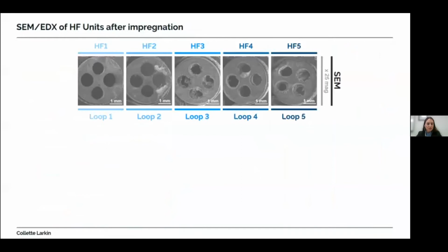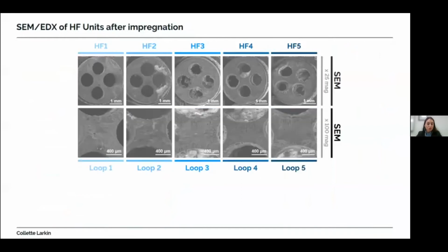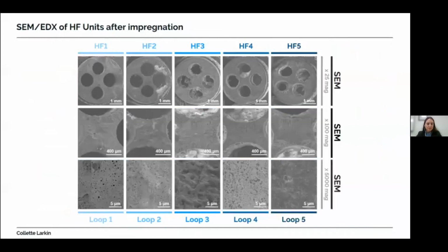And to get a better understanding of how increasing the number of impregnation loops physically affects the hollow fibre adsorption unit, SEM photos and EDX surface mapping images of the hollow fibre adsorption units after impregnation were obtained at magnifications of 25, 100, and 5,000 of the cross section of the hollow fibre adsorption units. And from the photos, it can be seen that the neat, open, porous structure becomes progressively filled as the number of impregnation loops are increased.